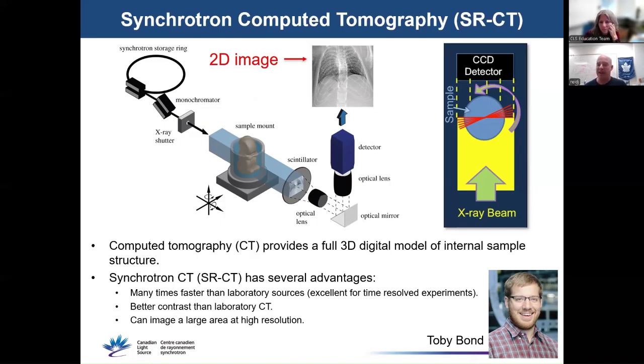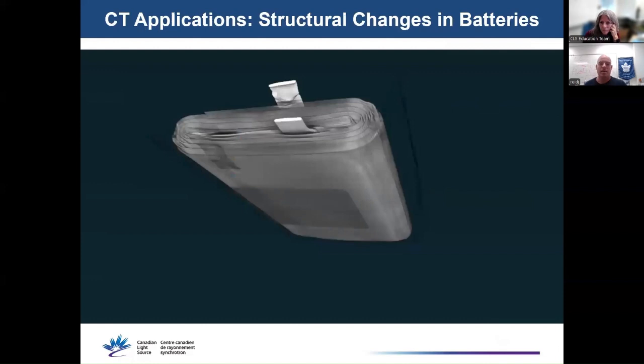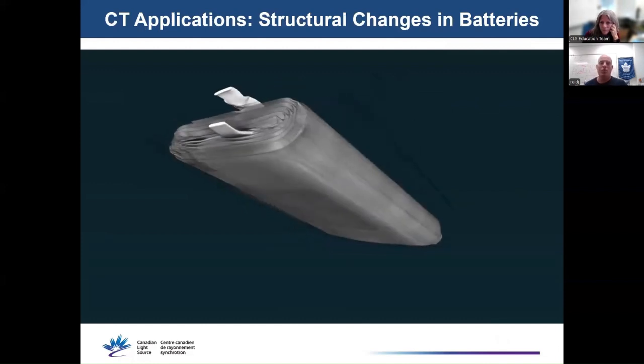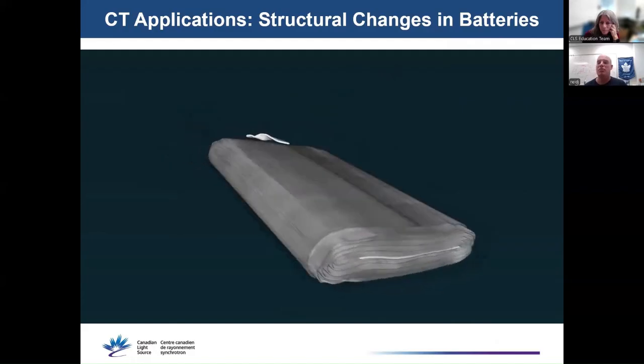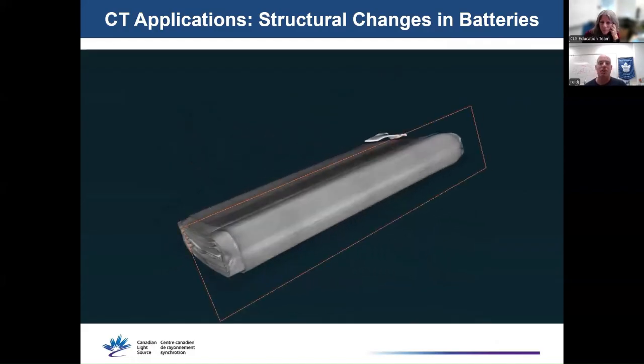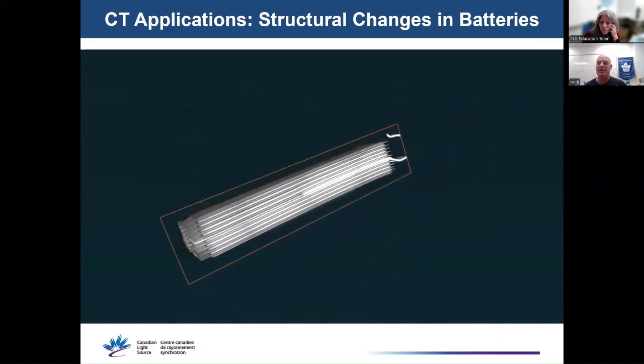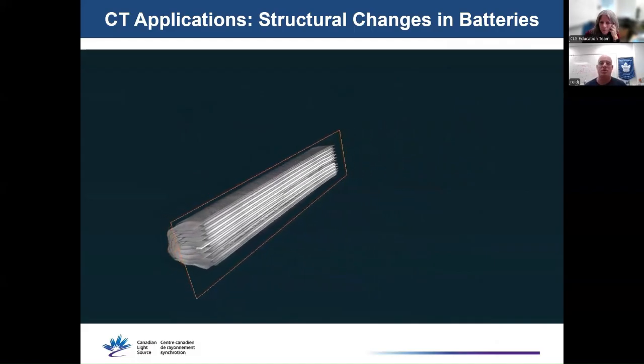Synchrotron CT is much faster than lab CT, which makes it very useful for time-resolved experiments. And tunable energy means that you can generally get better contrast than lab CT. You can also image larger areas, and you can image at higher resolution than you can with lab CT. So with computed tomography, we obtain a complete 3D rendering of the object, which can be sectioned or segmented as you need in order to answer your different questions.